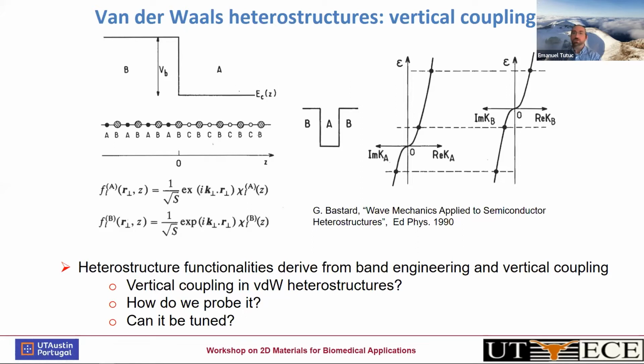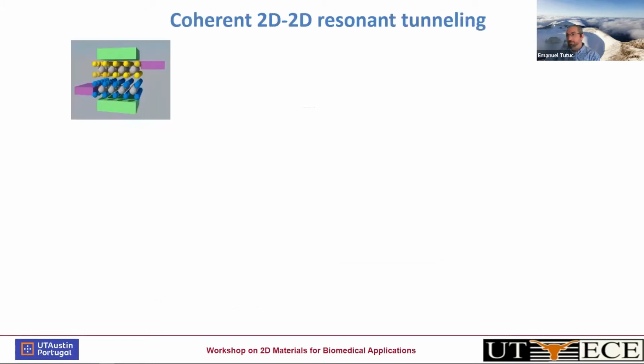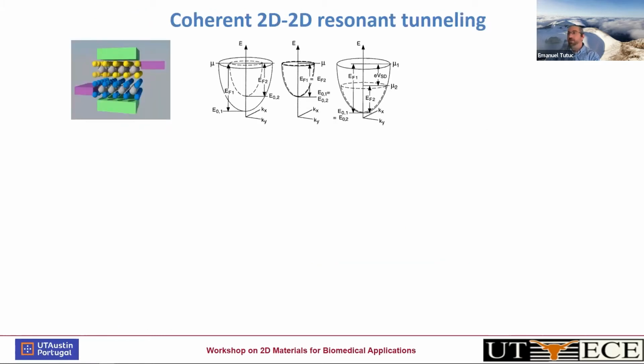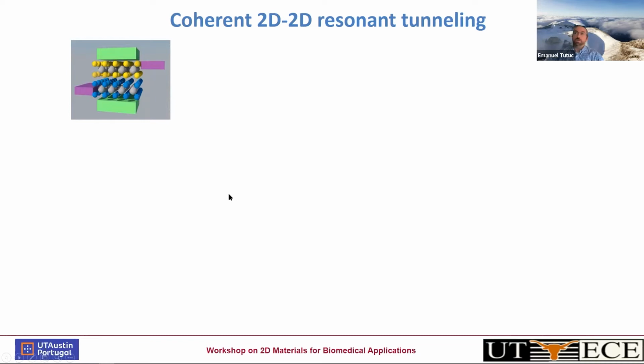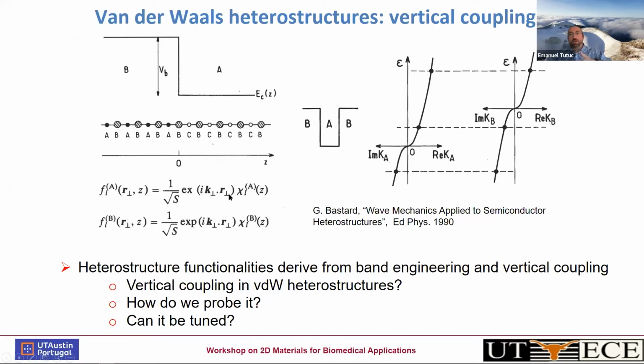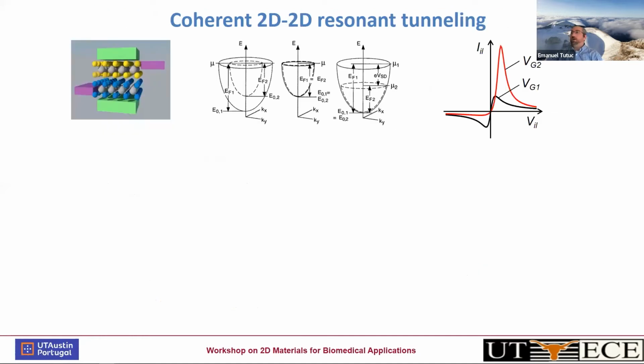In the heterostructure that we saw, where we have graphene bounded by hexagonal boron nitride, really the boron nitride is a passive actor, it's a dielectric. So the question that becomes right away is, can we implement something like this in 2D materials? And if so, how would we probe it? So I'll illustrate here a phenomenon that probes this and also allows a quantitative understanding of, for instance, coupling of one atom to the next one in the vertical direction. And this phenomenon is called resonant tunneling, and it can be pictorially illustrated in the manner shown here.